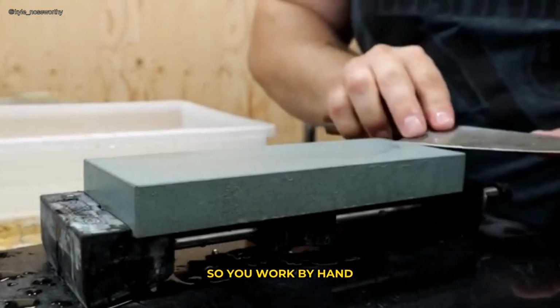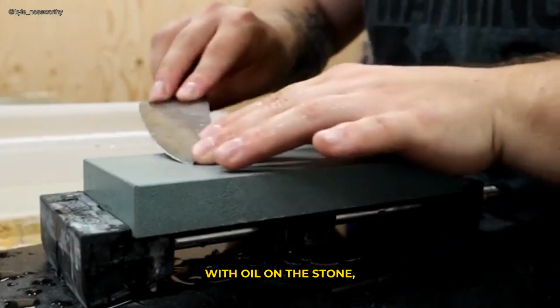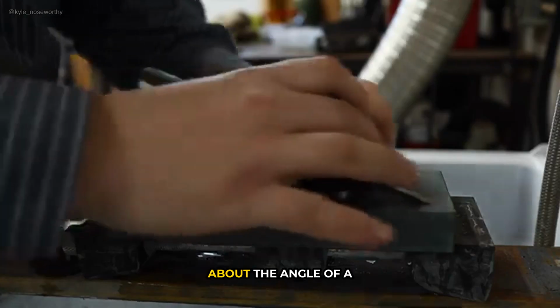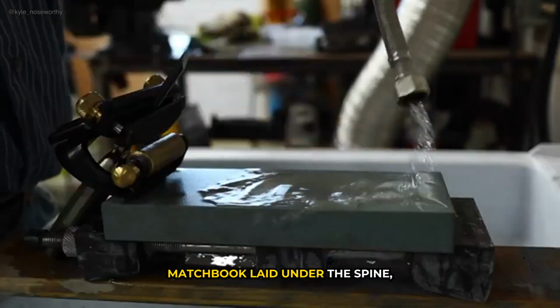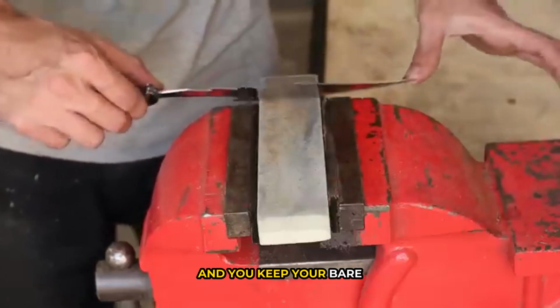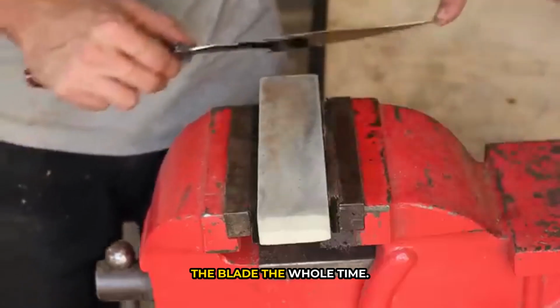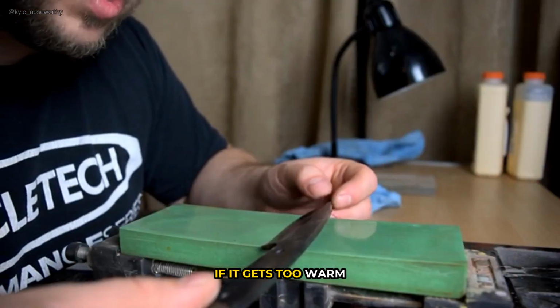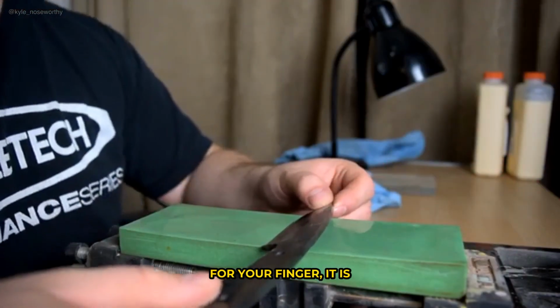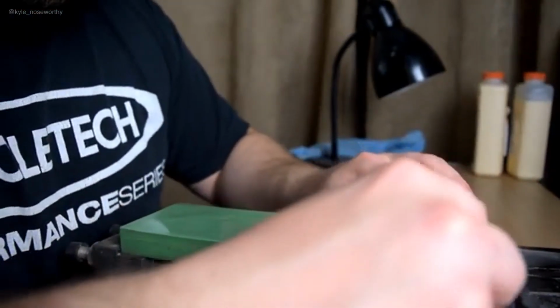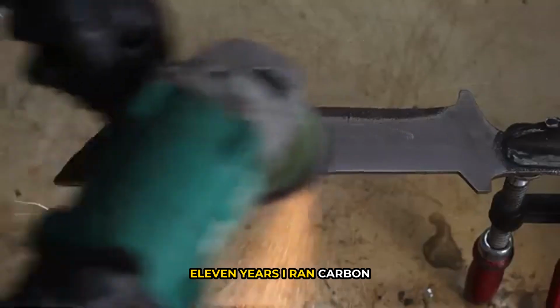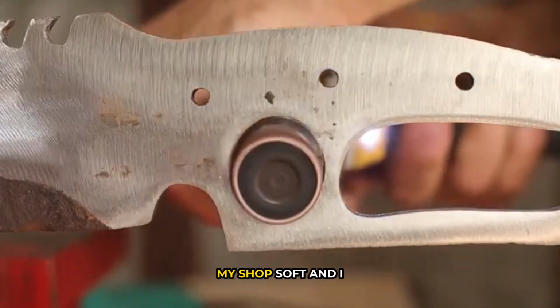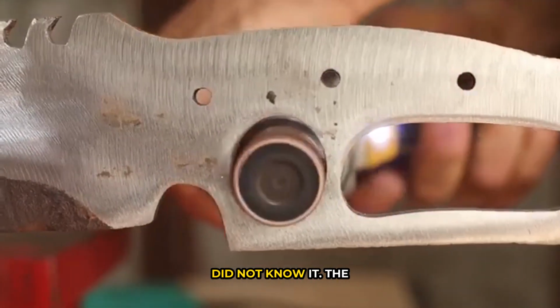So you work by hand, with oil on the stone, 20 strokes a side at about the angle of a matchbook laid under the spine, and you keep your bare finger on the flat of the blade the whole time. If it gets too warm for your finger, it is too warm for the steel. Eleven years I ran carbon blades on a grinder. Every one of them left my shop soft, and I did not know it.